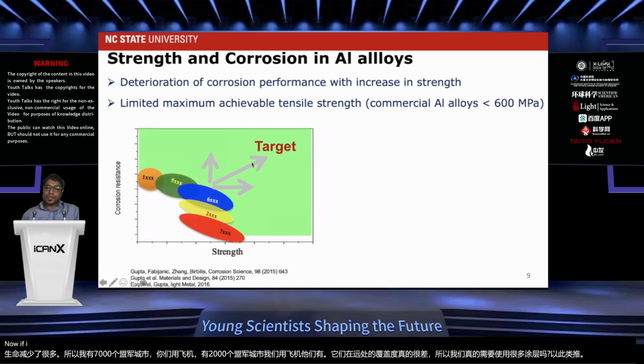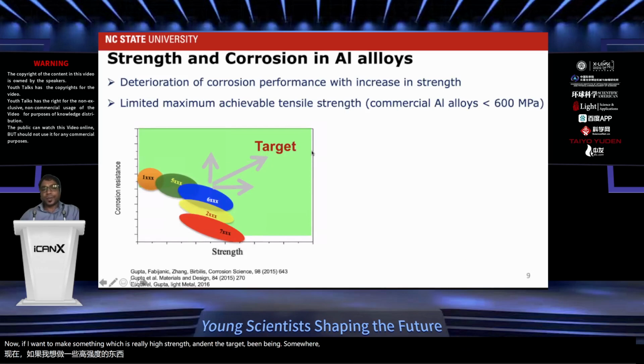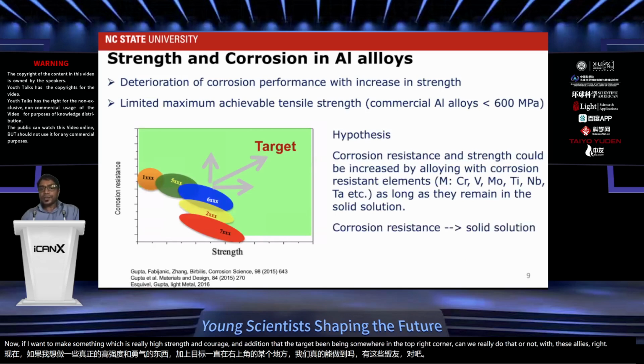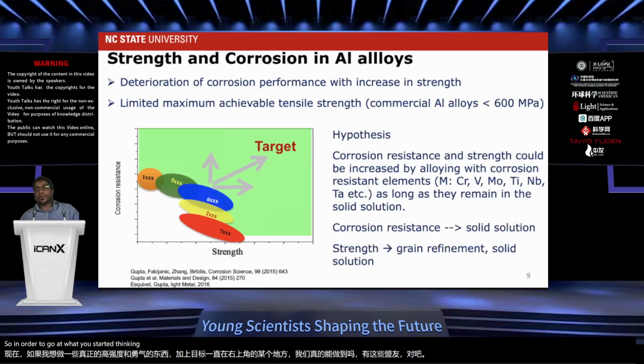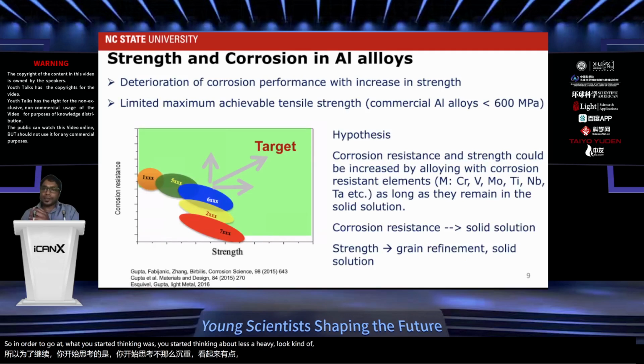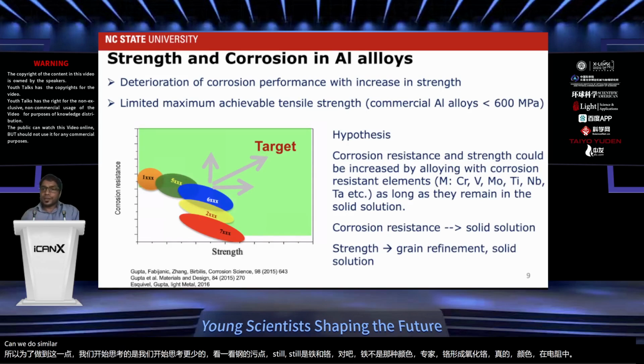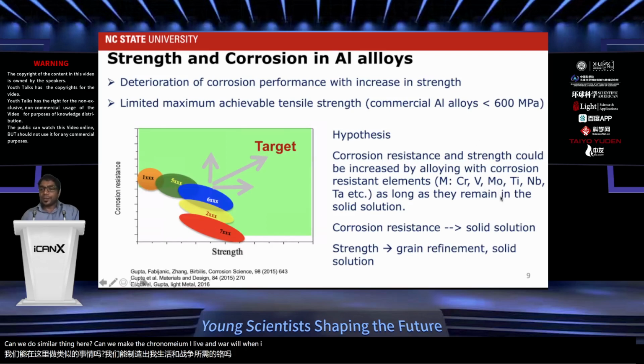Now, if I want to make something which is really high strength and corrosion resistant, the target is somewhere in the top right corner. Can we really do that with these alloys? So we started thinking, let's have a look at stainless steel. Stainless steel is iron and chromium. Iron is not that corrosion resistant, and chromium forms chromium oxide and is really corrosion resistant. Can we do a similar thing here? Can we make, say, aluminum chromium, aluminum vanadium, aluminum moly, putting in corrosion resistant elements and making a supersaturated solid solution?